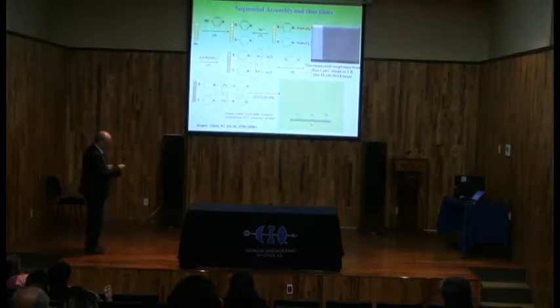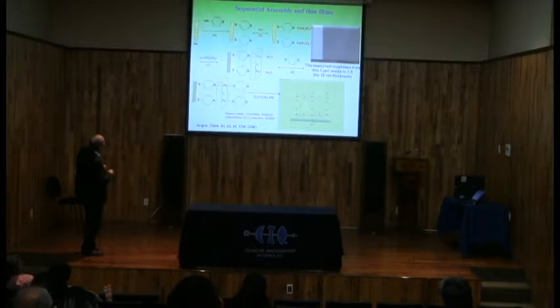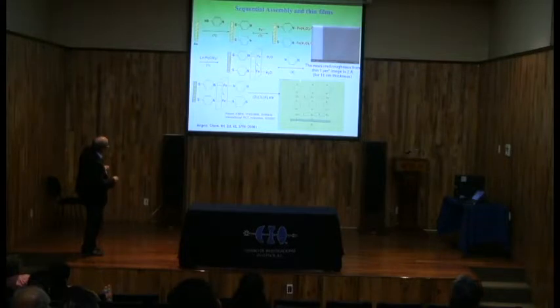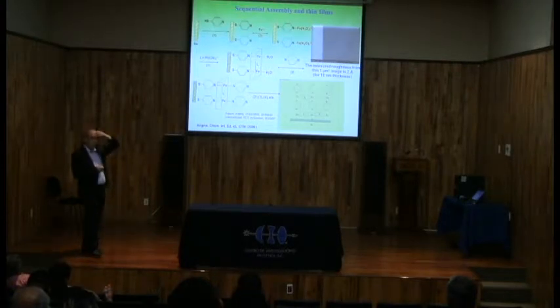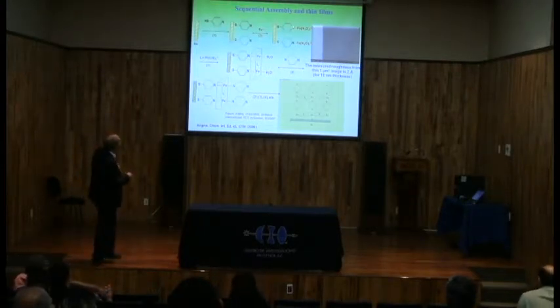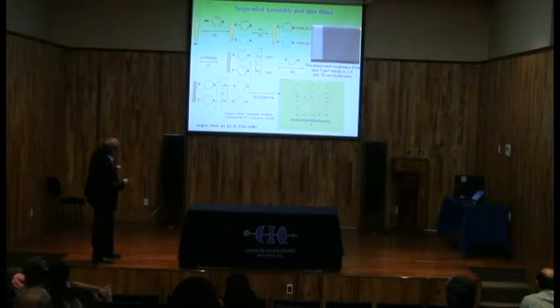So then we did the layer by layer synthesis. First step is to fix the mercaptopyridine on the gold surface, and then iron salt, and then the platinate here, and then we come back with pyrazine. If you turn here, as the number of the cycles, you can grow your film. Okay? And then when we use this technique, we could have very nice thin films here, okay?